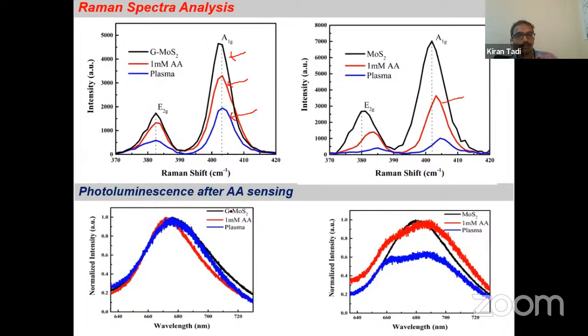You can also see the PL from the MoS2, comparing graphene-protected MoS2 and MoS2 alone. For the MoS2 protected with graphene, there is no disturbance, no decrease in the intensity of the PL. But you can see a decrease and splitting of the PL observed in the case of MoS2 alone.